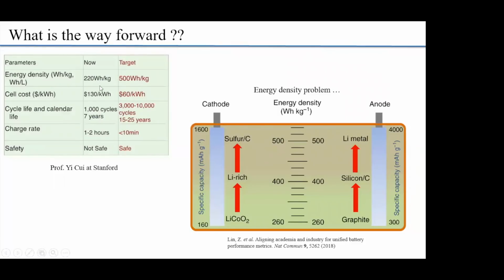This slide is from Professor Yi Cui at Stanford, and it is from the paper Aligning Academy and Industry for Unified Battery Performance. The way experts look at it is, right now we are at an energy density of around 250 to 260 watt-hours per kilogram using lithium cobalt oxide, which is the cathode used in the iPhone, and the graphite anode. Now, if you push that to lithium-rich cathodes, for example nickel-rich NMC811 or some other cathodes, and then move to a silicon-based anode, a silicon and carbon hybrid, then you're looking at about 350 to 400.